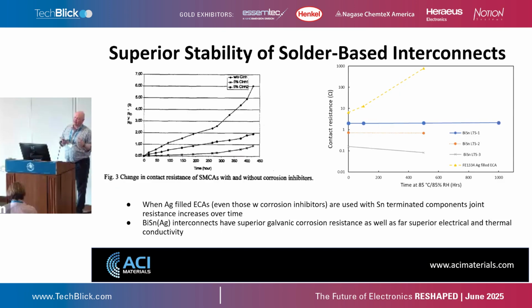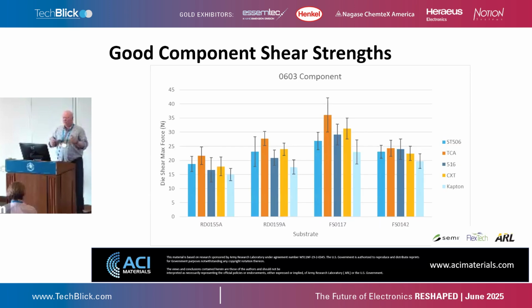And this is a slide that really shows that even the best silver-filled epoxies, they do start to rise in resistance on the joints. You start to get some corrosion with tin, for instance, whereas with solder, you get very stable connections with tin finished components. And we've done quite a long study on various finishes of polyester, TCA, that sort of acid etched matte polyester, ST505, 506, really almost bare polyester, and even Kapton, and looking at component shear with some various Alchemy inks. You're going to break your nail trying to get these 0603s off there. So very secure bonds to the surface.